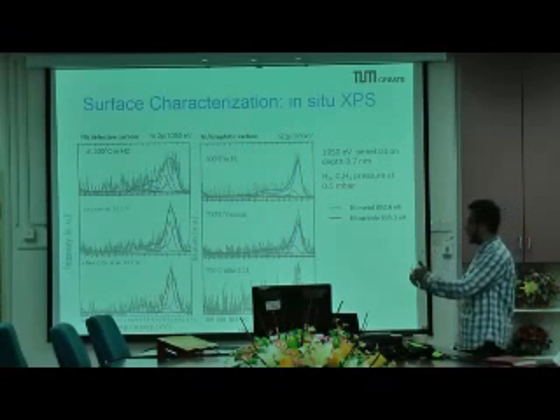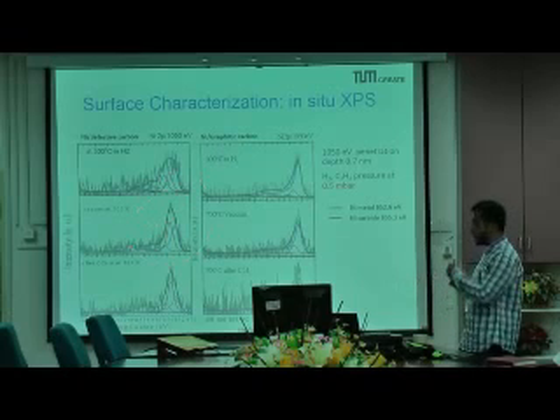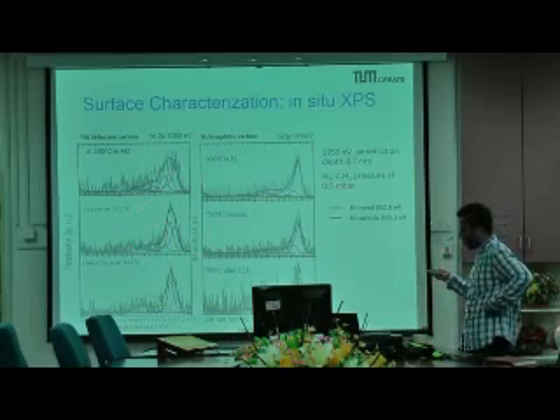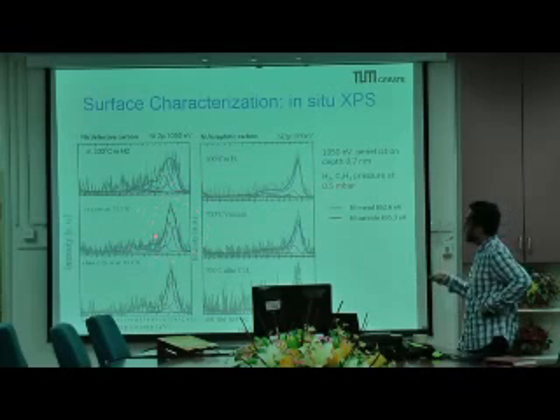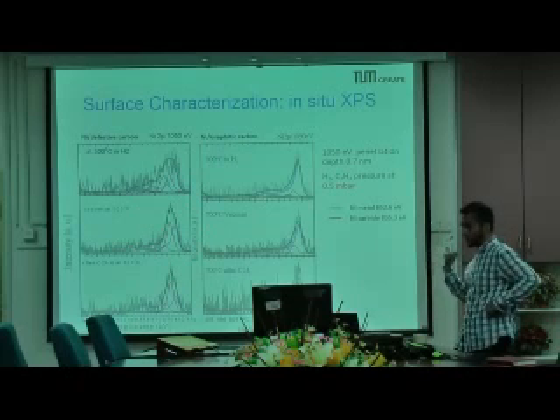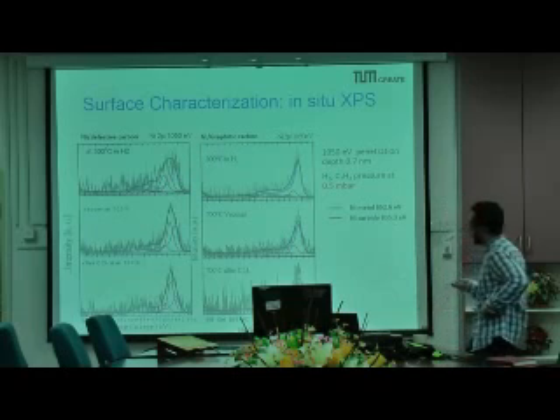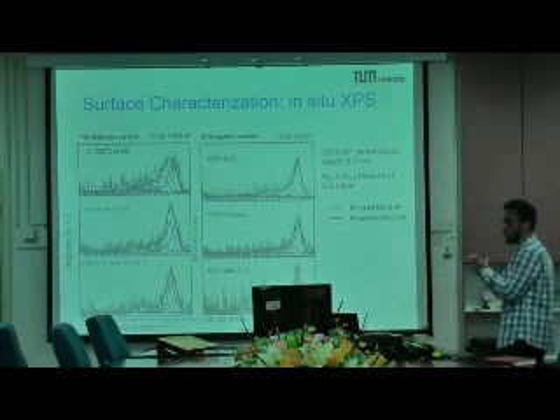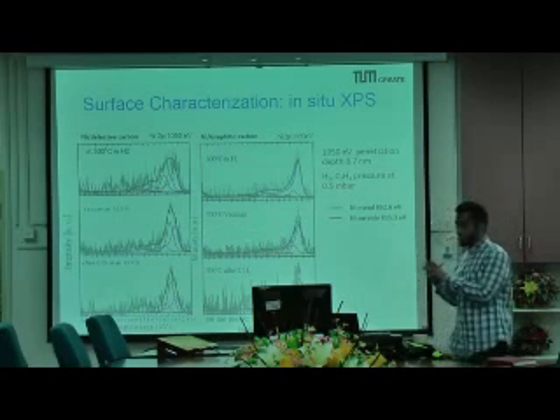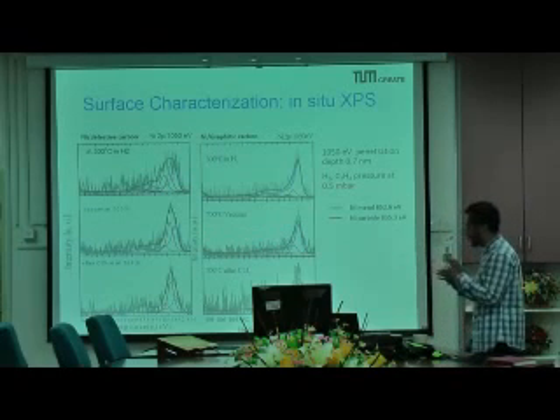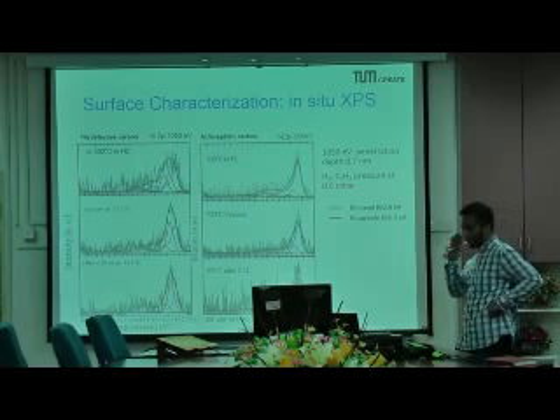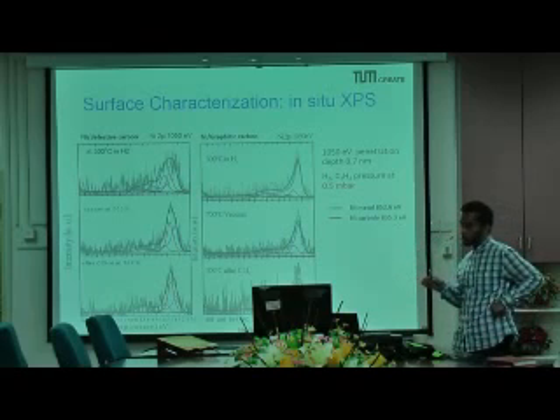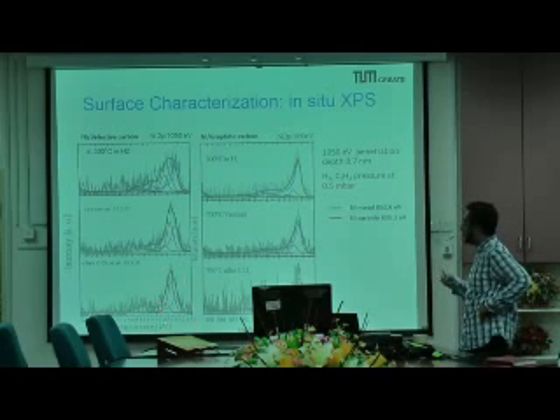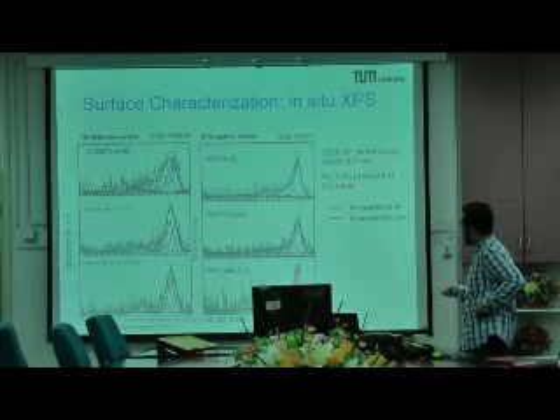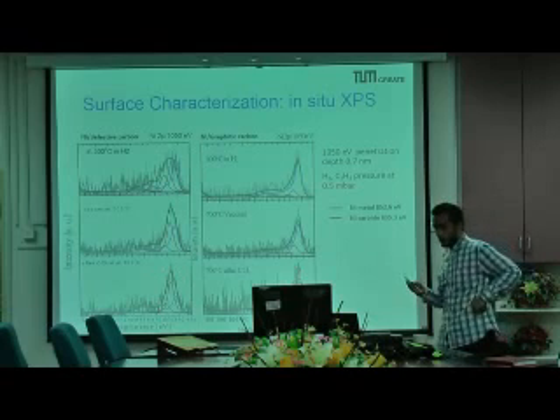If you increase the temperature in the vacuum, so no gas around in the reactor, the nickel carbide signal jumps up, suggesting that there's more carbide going into the nickel nanoparticles. Whereas in graphitic materials, the nickel stays relatively the same metallic feature. It gets even worse when ethylene is introduced into the system at 700 degrees. So the carbon dominates the nickel on defective carbon, whereas there is a significant amount of metallic features on the surface of the nanoparticles.